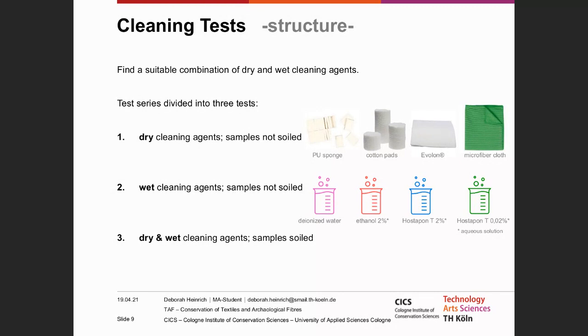In the second part, which was designed as a swelling test, I tested the wet cleaning agents listed on the right on non-soiled test samples. In the third part, I tested all dry and wet cleaning agents combined with each other on soiled test samples, whereby the cleaning effect was also examined. In the first two tests, I wanted to investigate the effects of the dry and wet cleaning agents on the material of the PVC film.